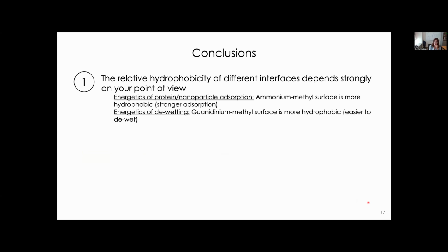So overall, some of our takeaways here were, first of all, that the relative hydrophobicity of these different interfaces depends strongly on your point of view, right? So the energetics of protein nanoparticle adsorption were pretty different than those of dewetting, and in particular, the ammonium methyl surface was more hydrophobic for adsorption, but not when we were looking at INDUS.